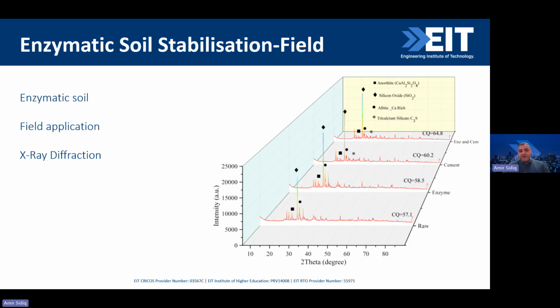Here, I did some XRD or X-ray diffraction tests, and the reason I wanted to do that is I just wanted to find the crystallinity of the clay particles or the crystals. So for the raw, it's actually 57.1, but then when you're adding the enzyme and cement together, we can see the crystallinity is actually becoming about 64. So the chemical bonding between the clay molecules is actually becoming very strong, which is leading to develop this crystal size much stronger. So I wanted to understand the crystallinity of these by using different additives. We're not talking about much of these scenarios, but my aim here was just to understand this crystallinity.